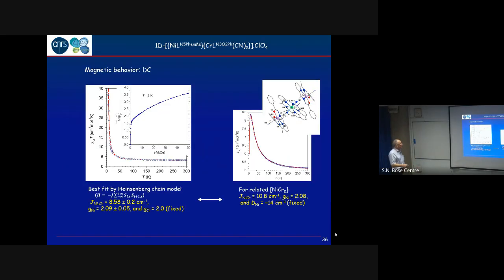So these are just some plots of the magnetic behavior. So here we have a typical behavior of a ferromagnetic chain. You see that as the temperature decreases, we have an increase of chi T. This is the M versus H curve with a very fast increase for very small field, again characteristic of a large magnetic moment. You can analyze this data to have an idea of the exchange interaction. So we find numbers around 8 inverse centimeter.